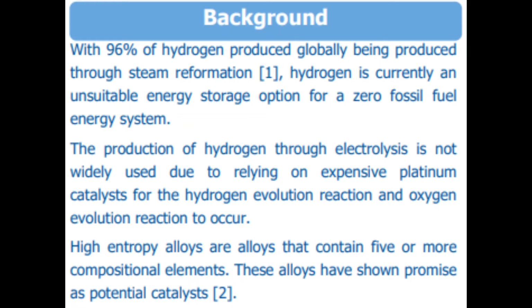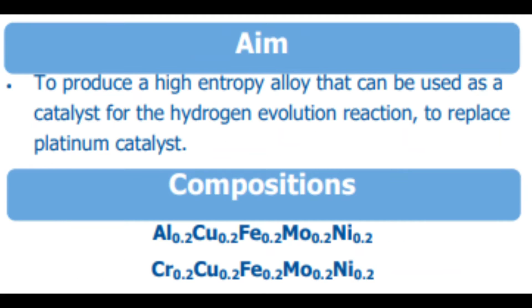However, there has been research conducted into high entropy alloys as catalysts for this hydrogen evolution reaction and oxygen evolution reaction. This has shown promise. The aim of my project was to be able to produce a high entropy alloy that could be successfully used as a catalyst for the hydrogen evolution reaction. Ideally, this catalyst would have catalytic abilities similar to those of platinum group catalysts and would eventually be able to replace them.